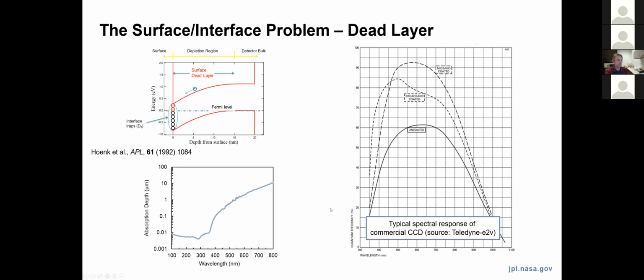these systems. So as Roger mentioned, if you take a silicon imaging sensor like a CCD or a CMOS sensor, there's a lot of electronics and front surface structures that would prevent you from using a front illuminated sensor in the UV, since those materials would absorb all of the photons that you're interested in. So you need to flip the detector around essentially and illuminate from the backside. If you do that with virtually any standard CCD or CMOS imager, you'll get a quantum efficiency curve that looks like the one I'm showing on the right here, that has high quantum efficiencies at visible wavelengths and then rapidly falls off as you move into the UV with little to no response below 200 to 300 nanometers.